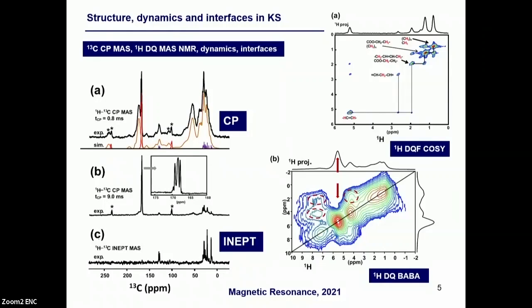There are as well very mobile species, and you can edit them very efficiently by using J-MAS-derived experiments such as INEPT. And in this case, it can be proved that they correspond to fatty acids. And if you want to further characterize this fatty acid, you go to a simple double quantum filter COSY experiment, and you can assign very safely all the correlations.